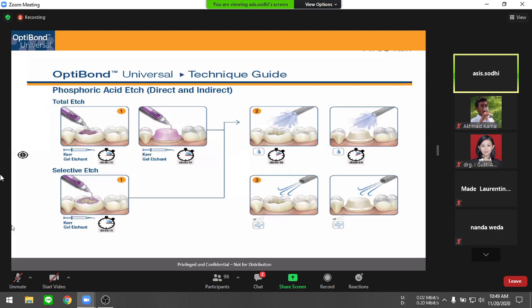Now, if you, for example, select a selective etch technique, when would you select a selective etch technique? Think about it. For example, a case which is a deep carious lesion. It is a deep class 1 or a deep class 2, where a lot of dentine is exposed on the floor of the cavity. However, there is also significant enamel on the cavo surface margin. So you want high bond strength from the enamel, right? So you are using a selective etch technique. You will use phosphoric acid only on the cavo surface margin, rinse and dry. You will not use phosphoric acid on the dentine. You will only use our bond on the dentine. Okay, so that is a selective etch technique where you selectively etch the enamel cavo surface margin.